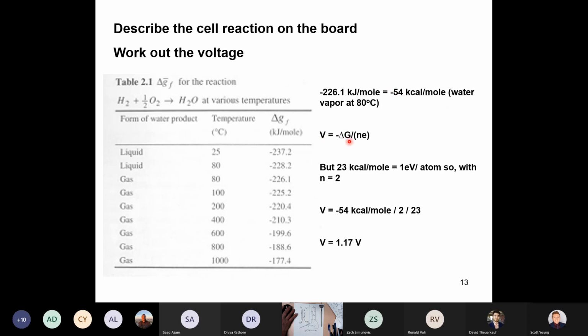And the voltage is minus delta G over NE. And you may not know, but 23 kilocalories per mole is 1 eV per atom. So with n = 2, you get 1.17 volts. Okay, so the open circuit voltage of a fuel cell should be around 1.17 volts. And it's kind of interesting, right? Because this is virtually equal to the electrochemical stability window of water, which is 1.23 volts.